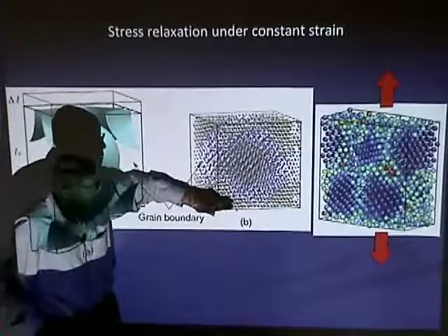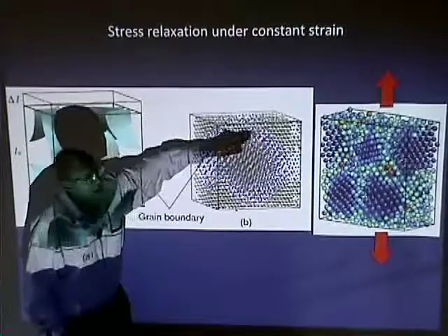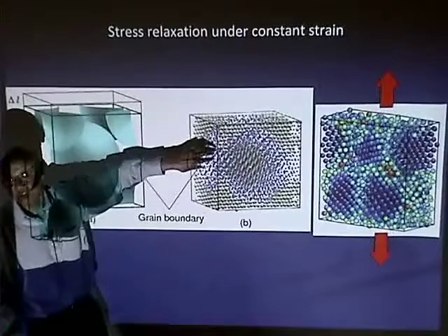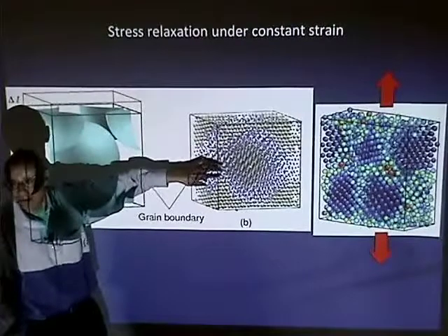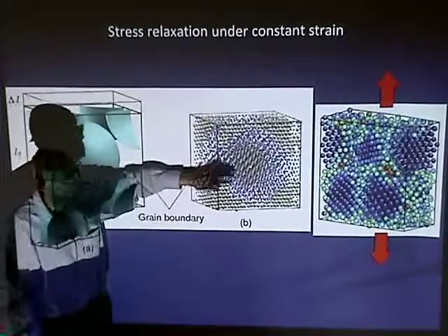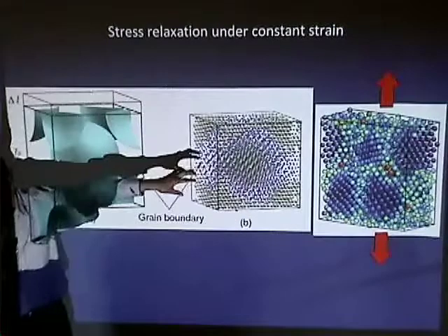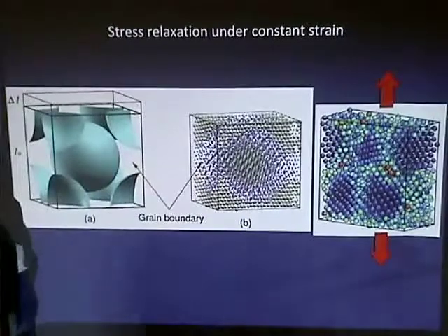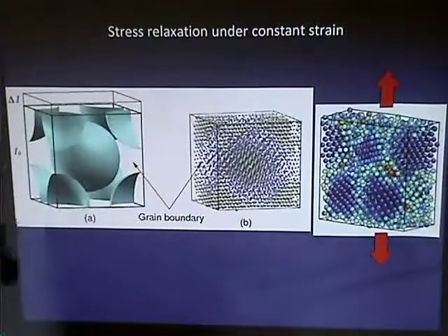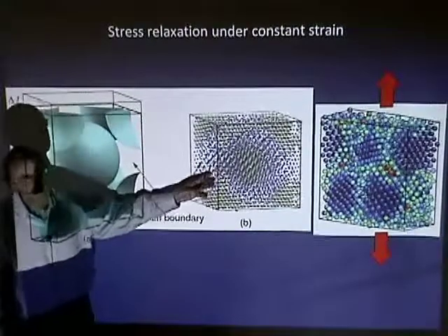So it's no surprise you start seeing atomic motion in response to strain happening in regions localized around the grain boundary. You can track this and figure it out. The interesting thing is that from the standpoint of simulation, you can look at stress relaxation over very long times, because the system is very perfect.